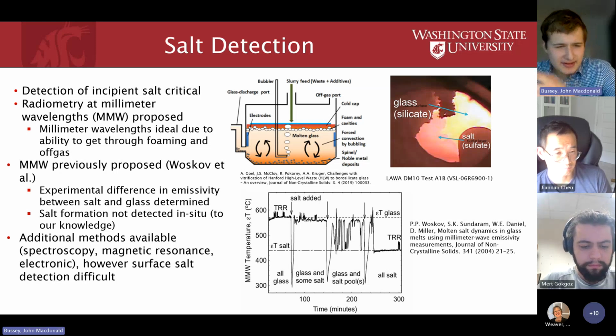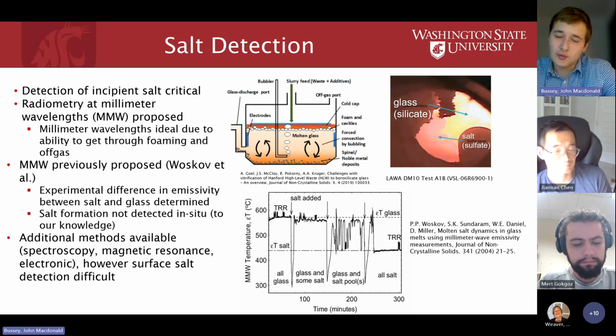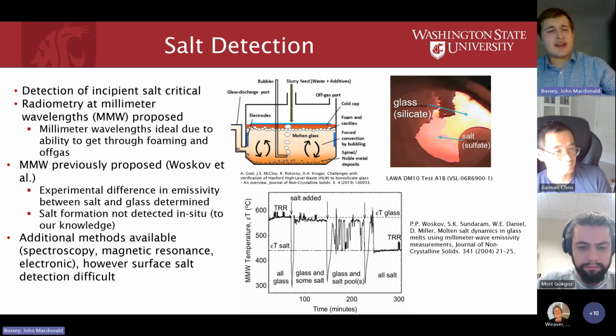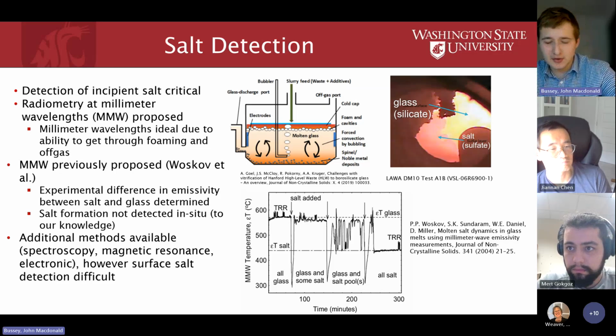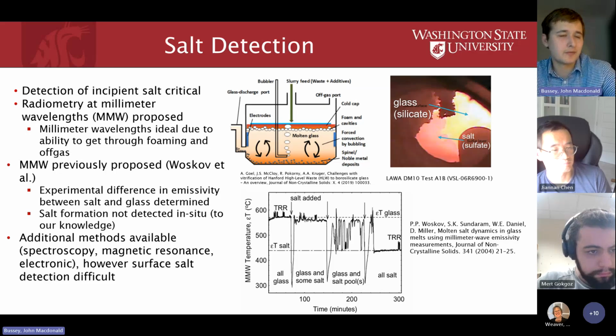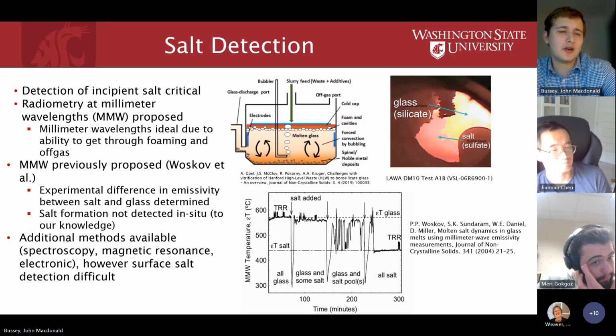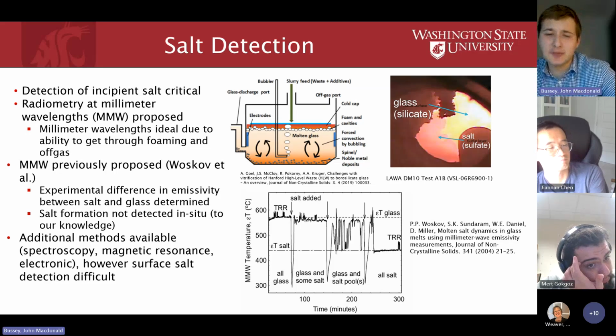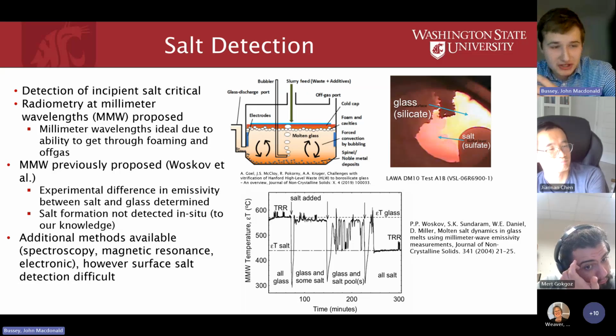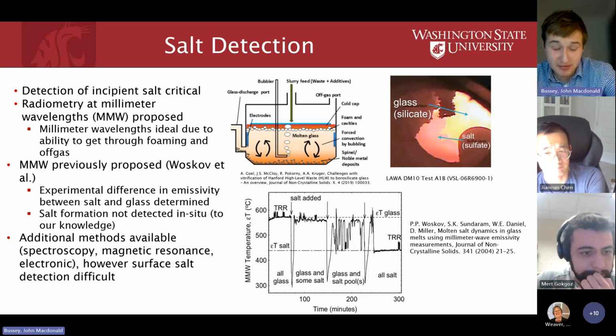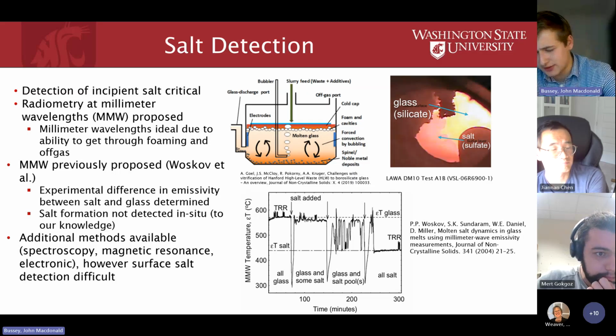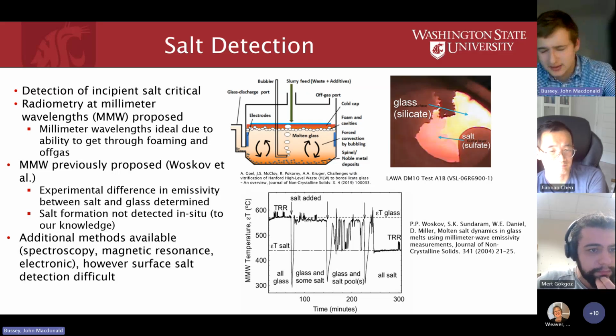So what we decided to work on is this method called millimeter wave radiometry, where you're using waves at millimeter wavelengths, so quite long, and then using them to look at the optical properties, the thermal emissions off the surface of your melt. And this has previously been proposed. A lot of work was already done, most of it led by Woskov out of MIT, looking at this to